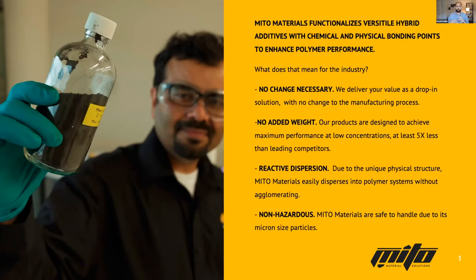Due to the chemical functional sites on our additives, it's reactive dispersion, so it blends out very, very nicely. I've done this on site with a drill and paint mixer from Lowe's, so it's very easy to use on site. And considering that the dry particle size is micron, and then it disperses out to submicron, it is non-hazardous. So you can wear standard personal protection equipment, like an N95 with safety glasses, totally fine.